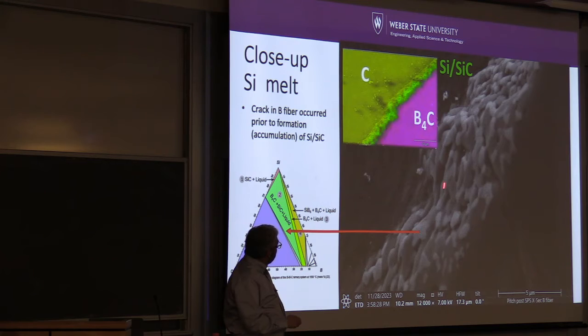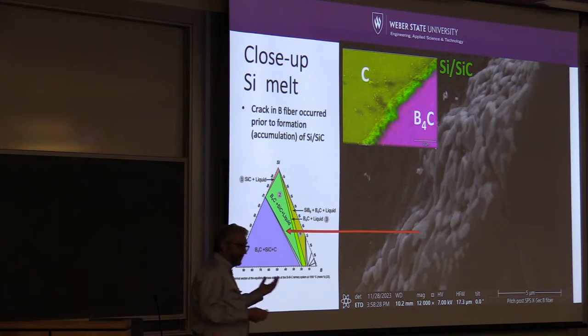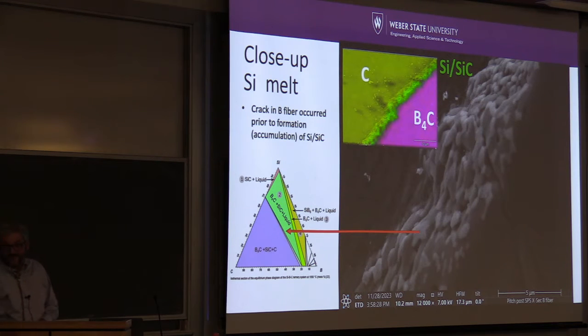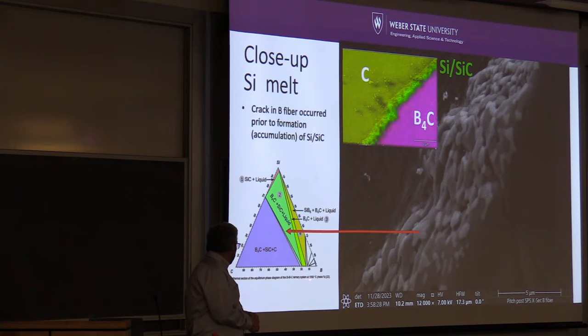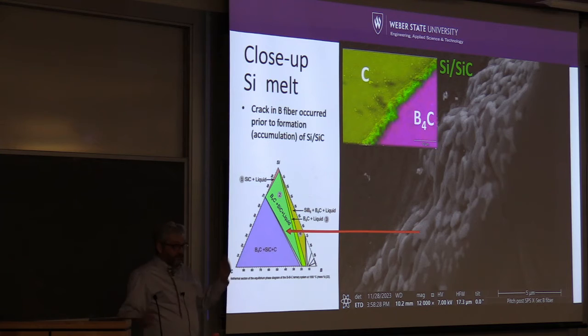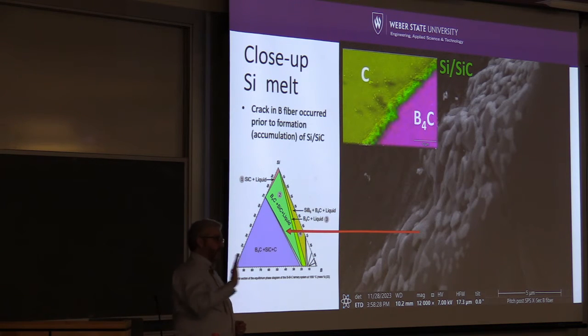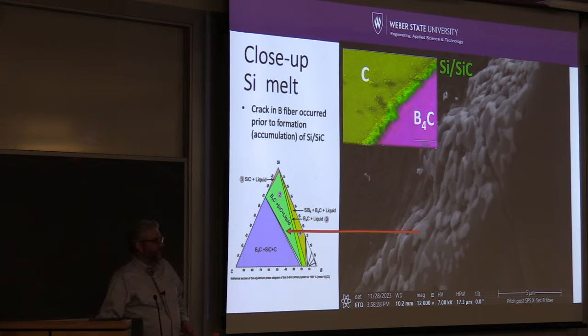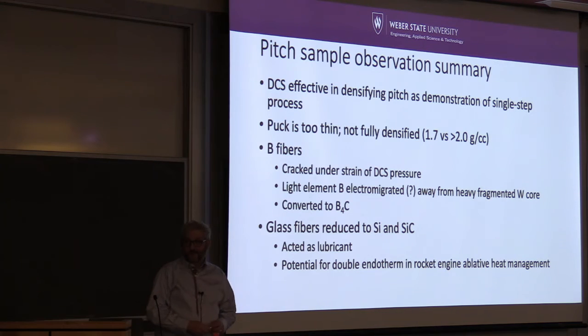And I can see that some of the silicon is silicon carbide, but there's a lot of silicon there that makes you go, what is going on, until you come over to your phase diagram and you say, what's going on in the phase diagram? And at about 1550, you got boron carbide, you got silicon carbide, and then you got liquid silicon. And so that's what we had here. And so all my glass fibers completely destroyed, melted, and that's not a huge surprise given the temperatures that we had. But it looks like also that the silicon acted like a lubricant for a lot of stuff just moving around. And it also looked like the electromigration effect just took that light boron and pushed it away from the tungsten. And so a lot of fun stuff going on right there.